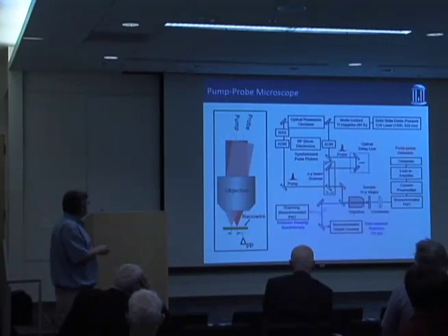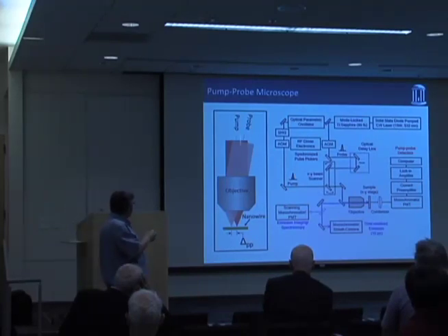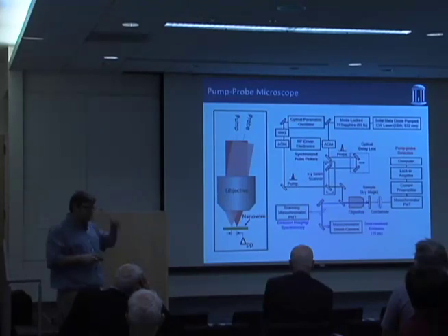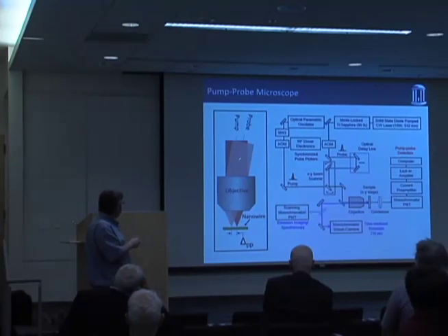The way we do it is, it turns out in this microscope, if I bring my pump and my probe in exactly collinear to each other, they're going to focus in exactly the same spatial spot. But if I bring the probe in at an angle relative to the pump, its focus is going to be offset laterally. So I can control the position, or scan the probe relative to the pump, simply by scanning the angle that the probe beam enters the objective. We do that with a couple of mirrors that scan that angle while keeping the beam centered on the back of the objective.